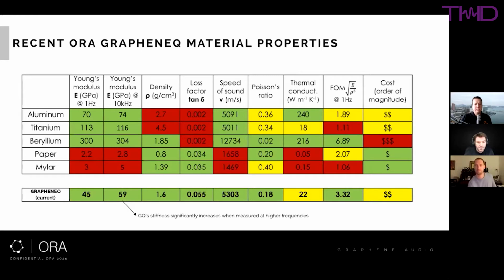And you've got Young's modulus there at 1 hertz and at 10 kilohertz. How is that measured? It's not a static tensile test, then. That's right. This is something that happens in polymers a lot, where you have a viscoelastic behavior, with a modulus that changes relative to frequency. And for ours, we actually get an increasing Young's modulus with increasing frequency, which is nice because we really need that additional stiffness at high frequency where loudspeaker breakup is likely to occur.